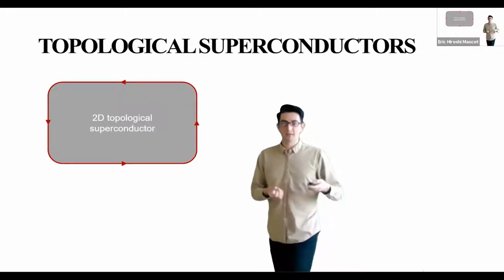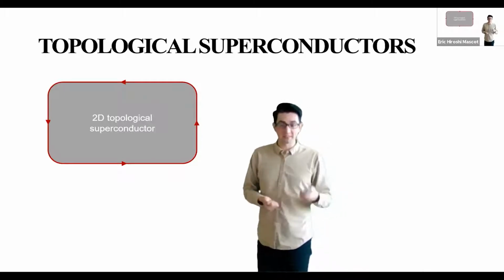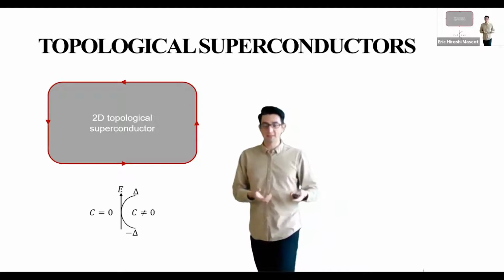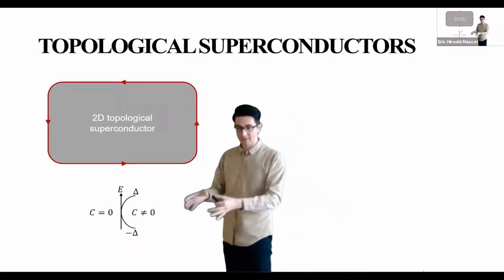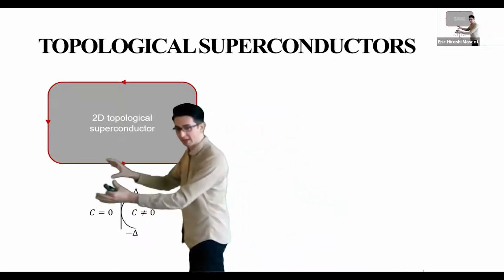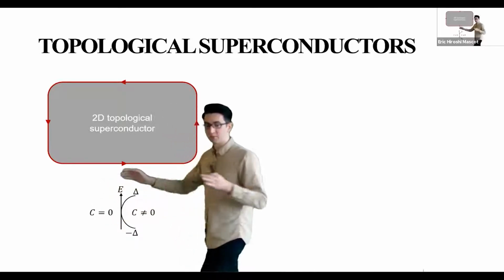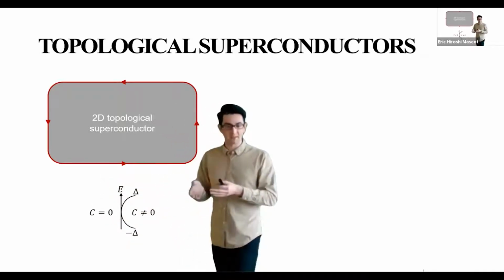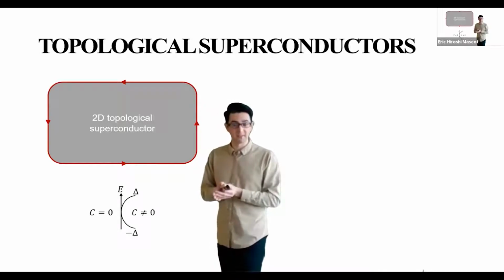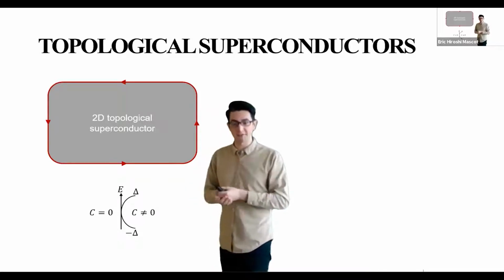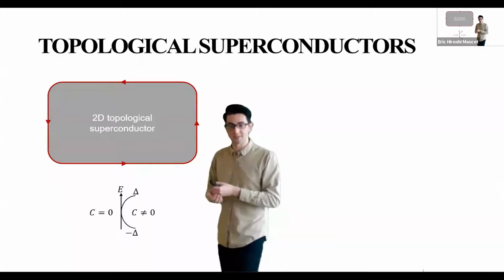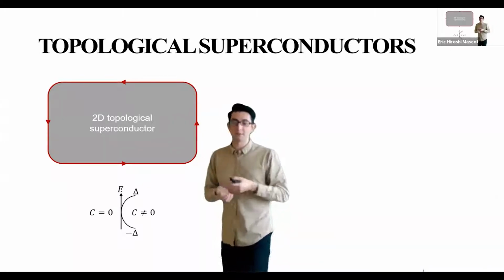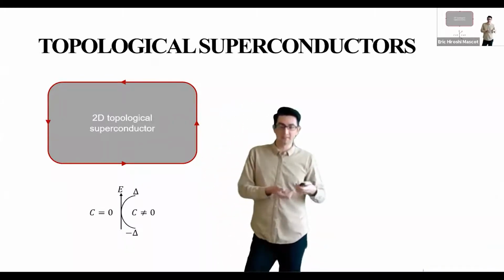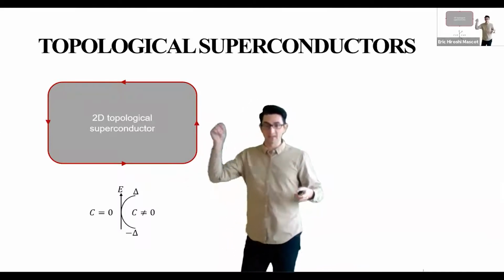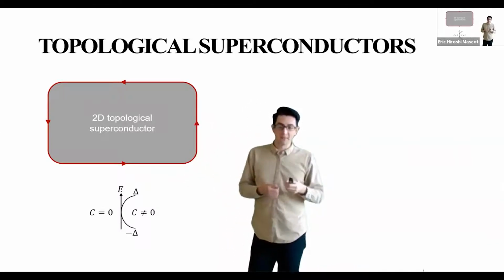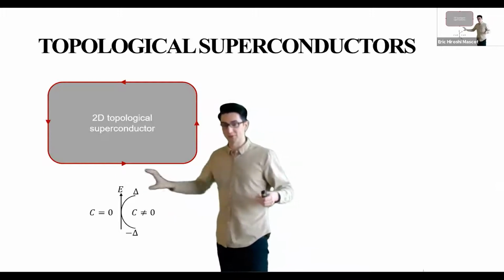So this chiral Majorana edge mode is a 0 energy state, and you get this because at the boundary you have a topological side, and then you have a trivial vacuum. So at the interface, you have to have a phase transition, which means that you have to close the energy gap. And so you get a 0 energy state. And there's something called the bulk boundary correspondence that says that the number of these edge channels is equal to the difference in these Chern numbers.